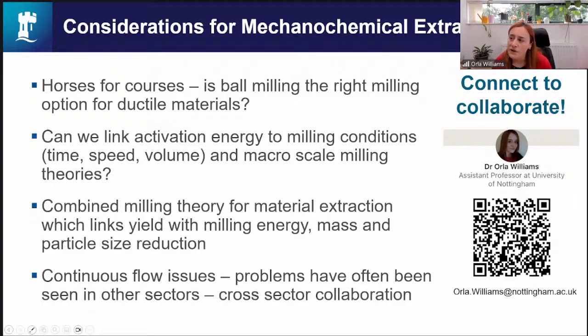I think for these materials, they are quite rough. I think it depends what scale of roughness you're talking about. It would be as much to do with whether they're brittle or ductile, and the deformation and the opportunities for fracture, are they exposed? For instance, if we look at coal, it has a fracture structure mechanism on the surface, so it's where those imperfections are in the materials. If your work is looking at a lot of reagents, then that would matter less, but there are always imperfections in every material. And understanding how perfect or imperfect your material is will influence those activation energies, because the less perfect they are, the more energy you'll need to break them down.